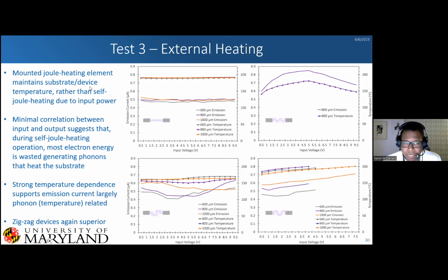through external heating. So we were saying, okay, well, all of our devices are self-joule heating. What if we provided the heat? What kind of emission will we get out? And interestingly enough, when we did use our external heater to heat it up to around 150 C, we got even more emission out of our devices that we didn't have to supply ourselves. And so for our devices in the future, I think that's what we would end up going with: instead of having self-joule heating, just have an external heater that we can use to optimize the emission current out of our devices.